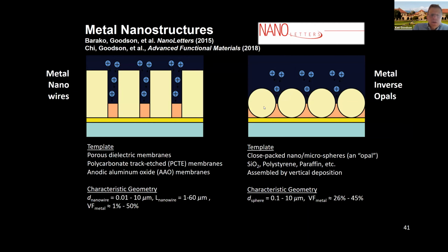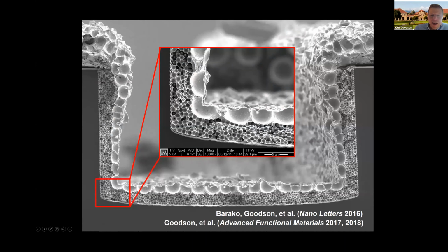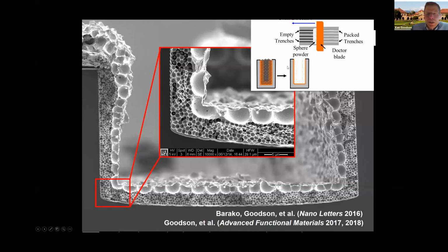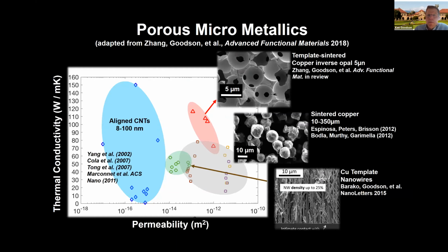medium. And you can do it inside a channel, because you can electroplate along the walls of the channel, and through subsequent electroplating events you can change, for example, the pore size. And this shows an example. You pack a fluidic channel with these polystyrene spheres, and then you electroplate from the perimeter, and then you are able to get this kind of conformal coating around the sides. So that's a fun way to make progress in this regard.